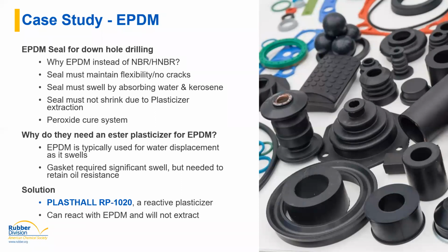EPDM in this application, though, typically swells for water displacement, but in this case they also needed something that would retain at least some level of oil resistance. And process oils obviously will not be very resistant to oil because they're very, very similar in their chemical structure. So they wanted an ester to help offset that.